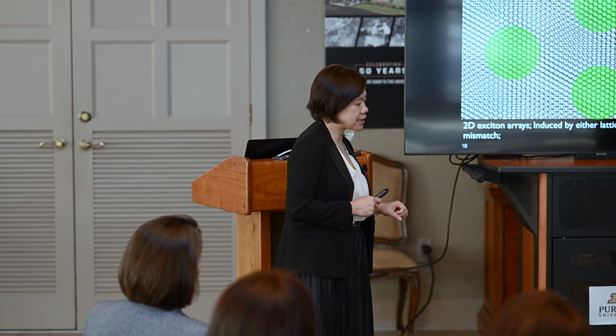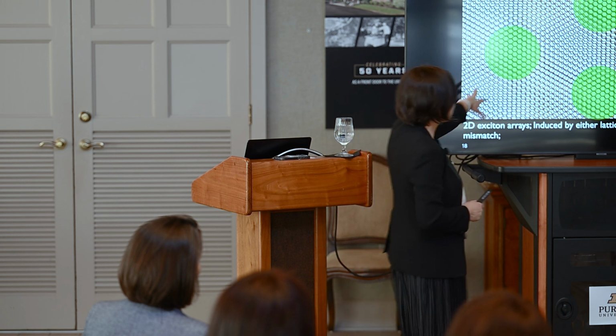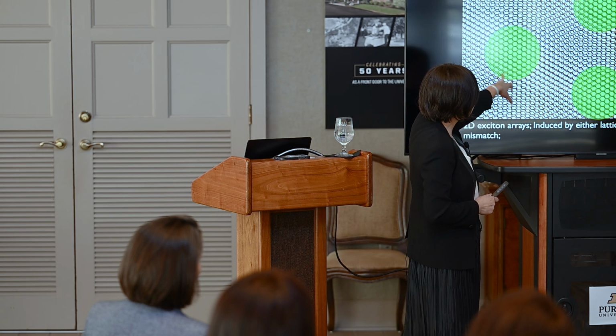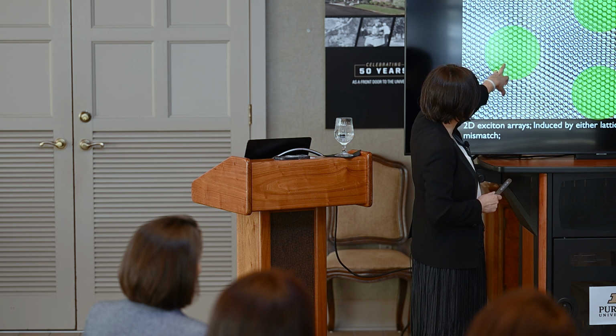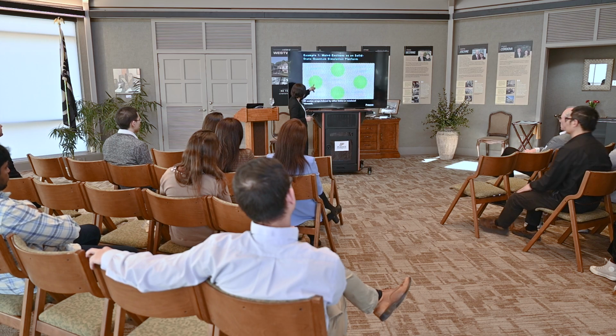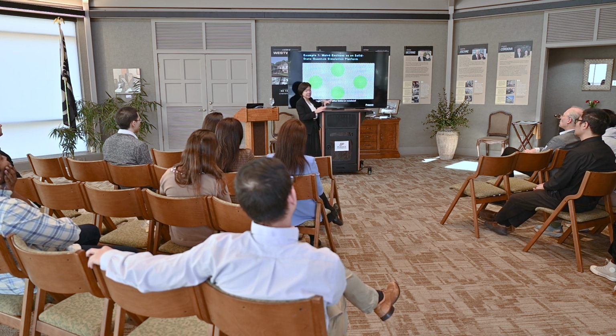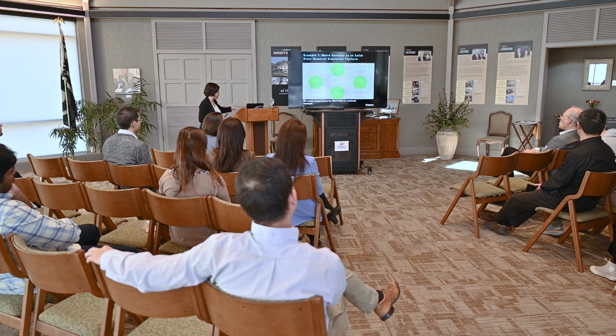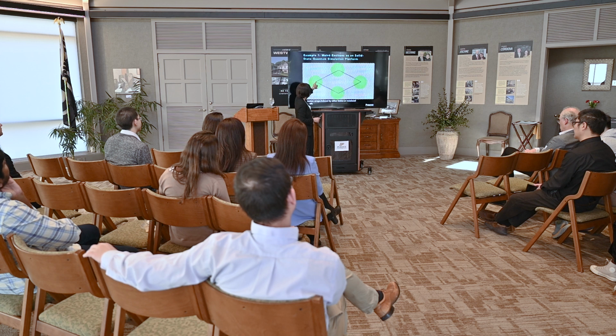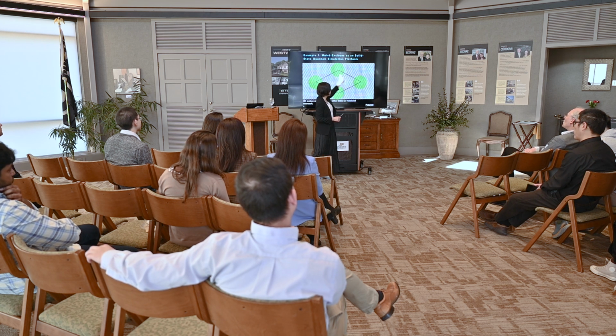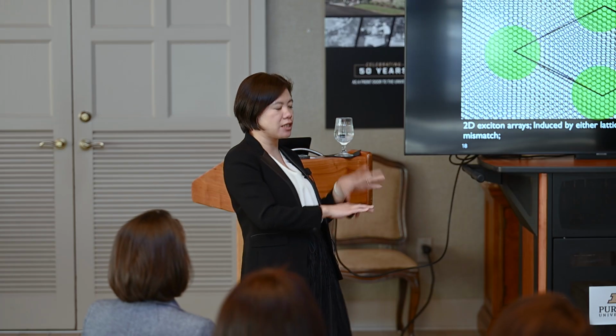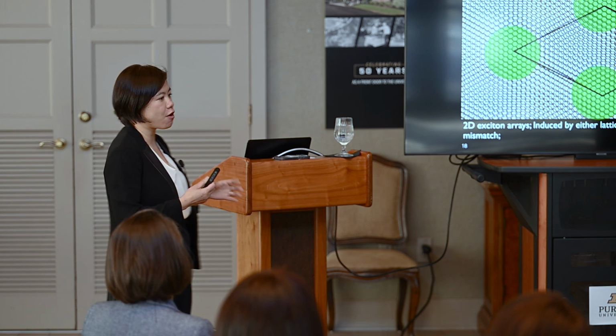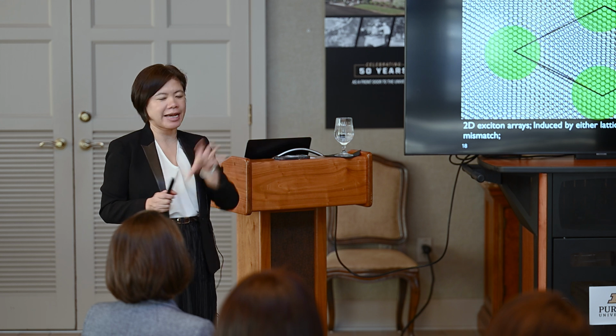What it does is create a way of generating an array of excitons, because at this green circle the structure is slightly different: the hexagonal patterns are right on top of each other, and away from the green dot they're slightly offset. The interaction between the two layers leads to a different energy landscape for the excitons. You can imagine the exciton would be located in certain areas of this lattice, and you can control that interaction by either twisting the lattice slightly or using different materials. This gives you a platform for looking at many excitons in an organized array.